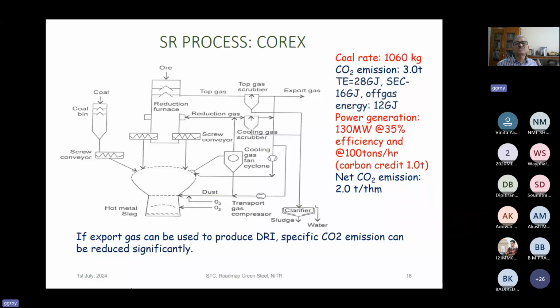Then another process is the smelting reduction process, the Corex process. If you see, the Corex also has a very high coal rate, 1060 kg, and the CO2 emission can be 3 ton, with total energy 28 gigajoule, SEC 16 gigajoule, and off-gas energy 12 gigajoule. And if you do the power generation at 130 megawatt and 35% efficiency from the primary energy source, that is coal, and if you produce at 100 tons per